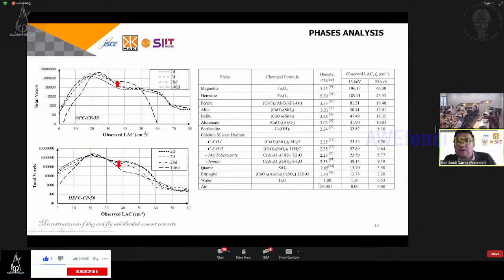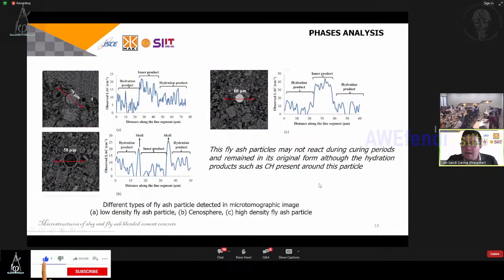I think it's easier to use, to explore, and to evaluate compared to XRD. And the second, as several presenters say, by using the SEM you can find the fly ash particle. In X-ray CT, you can differentiate several types of fly ash. Here, we found a lower density fly ash and a high density fly ash. And finally, we have a cenosphere, with high density in the outer and void in the inner. There are cenospheres as well as plerospheres in the fly ash. This cenosphere may contribute to high porosity in the fly ash sample.